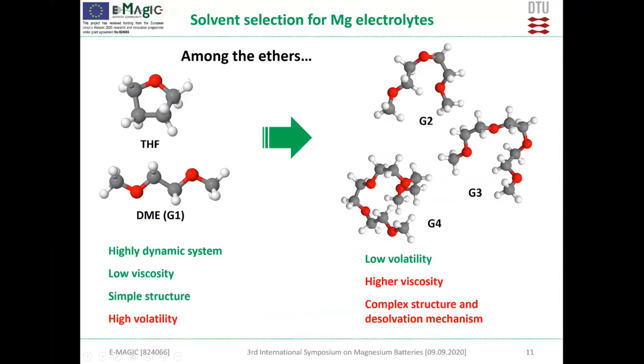And here, first, we noticed that the community usually uses THF or monoglyme because the solvents are quite simple, creating simple structures that you can easily determine even with XRD. They give high diffusivity and low viscosity, but the problem with them is that they also have high volatility because the boiling point is quite low. So that means if your battery starts to heat up, there could be a very dangerous situation.